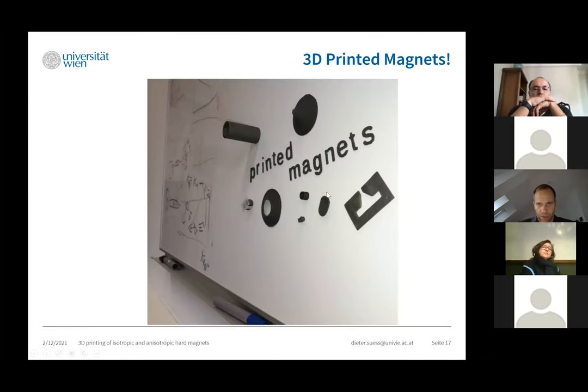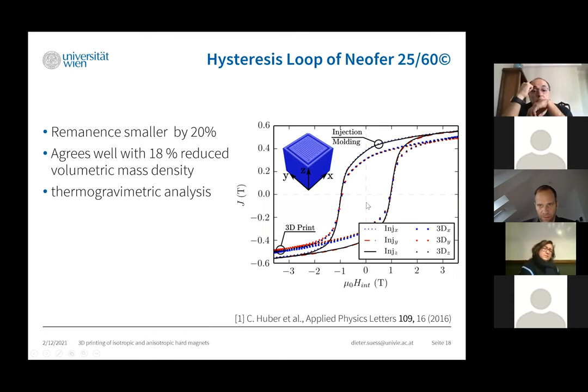If we now compare our printed magnets with the hysteresis loop of injection molded magnets, we see that the coercive field is very similar. So we get basically the same coercive field, which is not a surprise because we used exactly the same material, but the remanence is a little bit smaller in the 3D printed magnets because we also have about 18% reduced volumetric mass density.